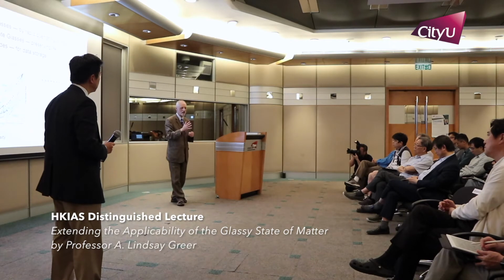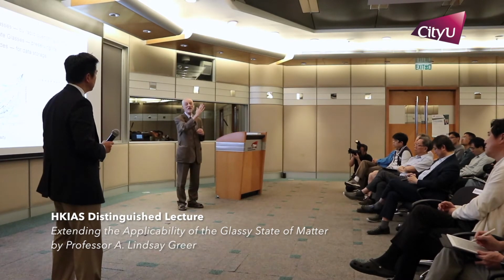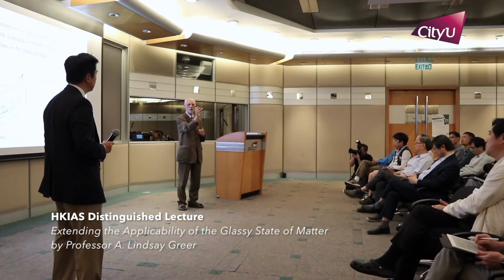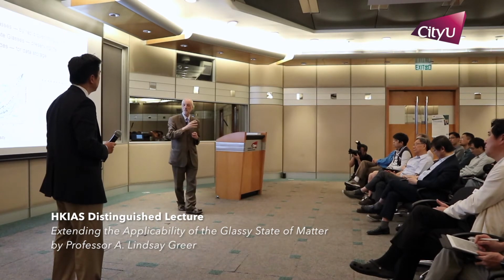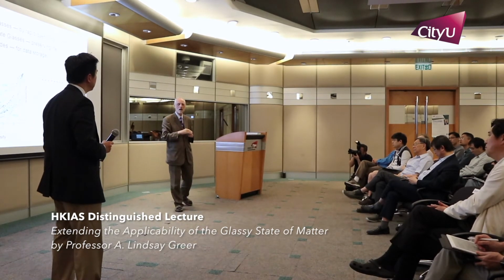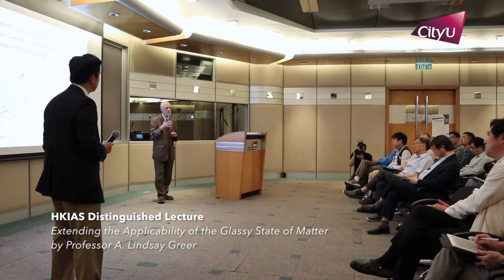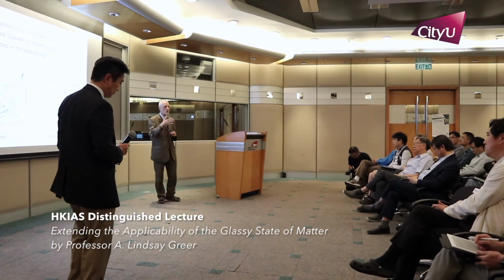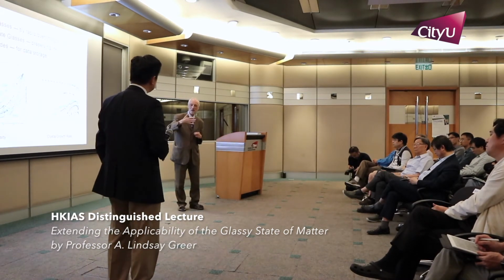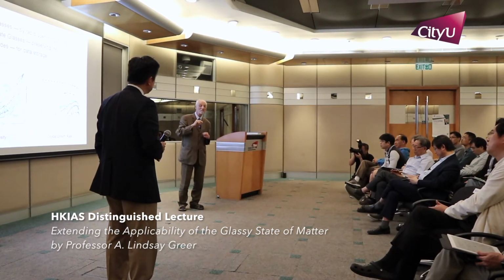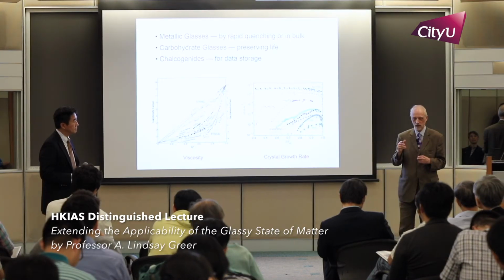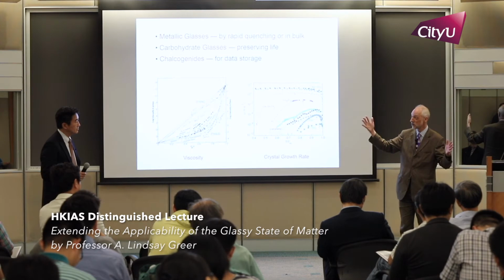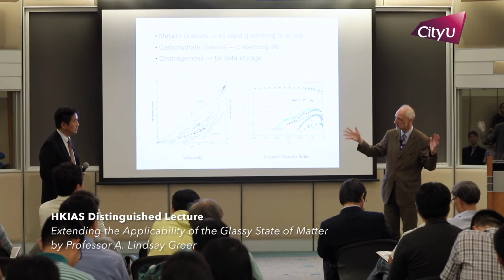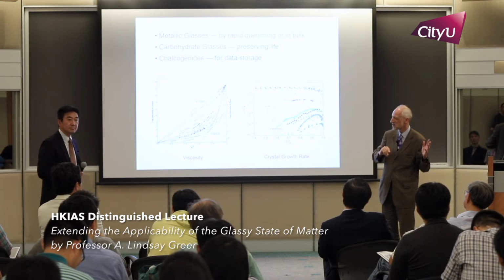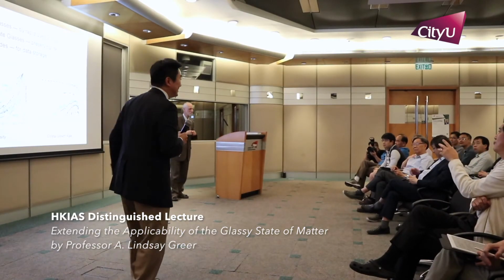And what Turnbull showed rather nicely, of course, is it's not really the atoms that move, it's the interface that moves. An individual atom doesn't have any need to make a diffusion jump. It just has to shuffle a little bit to fit into place, to fit the crystal rather than the liquid. And his idea was that the limiting velocity for that would be much more like the speed of sound. So you'd then be a few thousand meters per second as your limiting velocity. Well, we're pretty sure that's wrong as well. And so actually the real answer for the limiting velocity is between those two, between 10 and 5,000 meters per second. There's no good model at this point for saying. That's a good problem for the students.